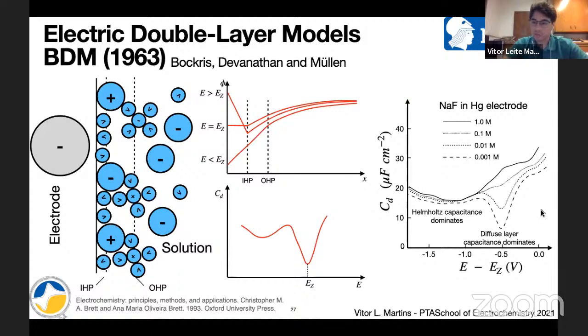So just to remind you that with this experiment here with sodium fluoride, we see that the diffuse layer capacitance dominates the region of the potential of zero charge, and that the Helmholtz capacitance will dominate the region of larger potential, right?